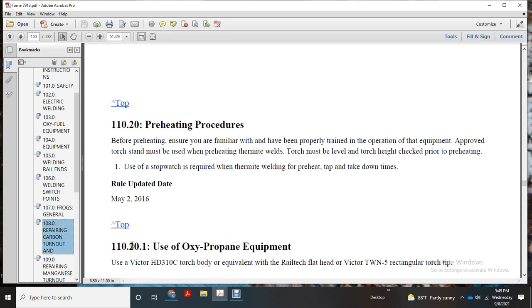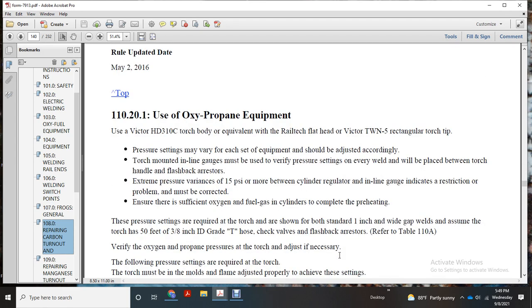Use oxy-propane equipment. Use the Victor HD310C torch body, or equivalent, with the Railtech flat head or Victor TWN-5 rectangular torch tip. Pressure settings may vary with each weld. The equipment should be adjusted accordingly with the torch-mounted inline gauges, which must be verified. The pressure settings on every weld will be placed between the torch handle and the flashback arrestor. Extreme pressure variances of more than 15 psi between the cylinder regulator and inline gauges indicate restriction problems that must be corrected.